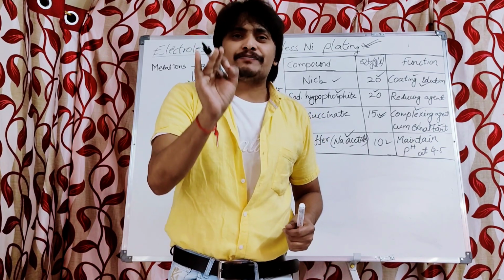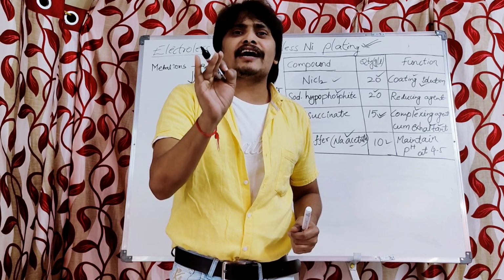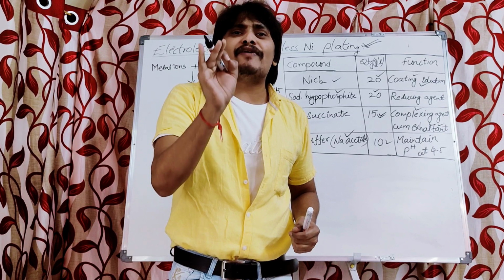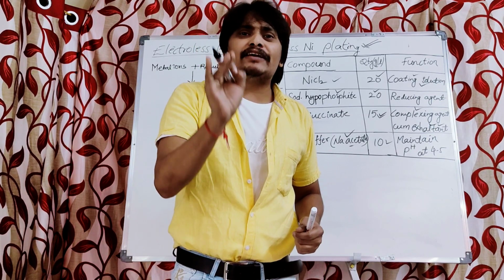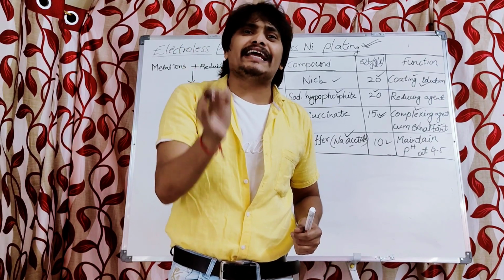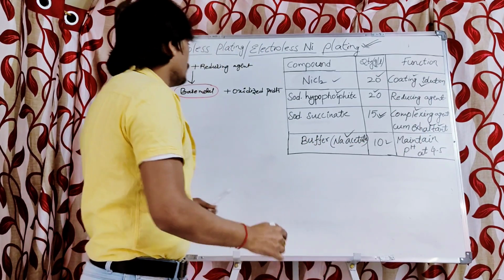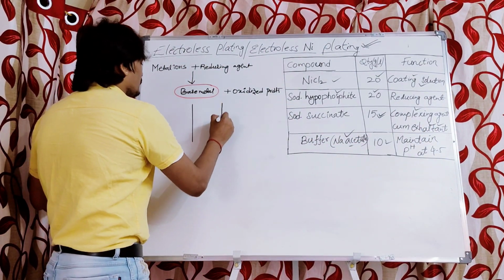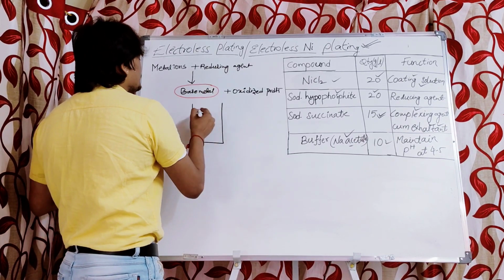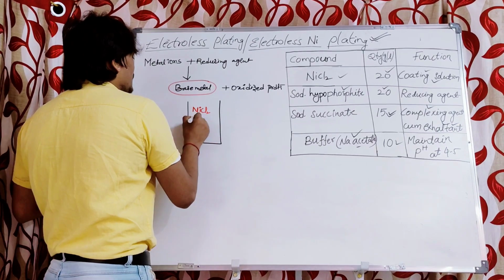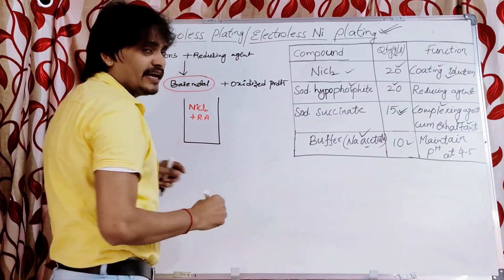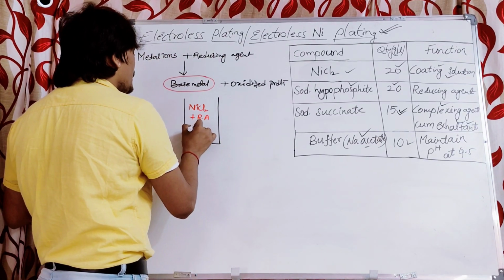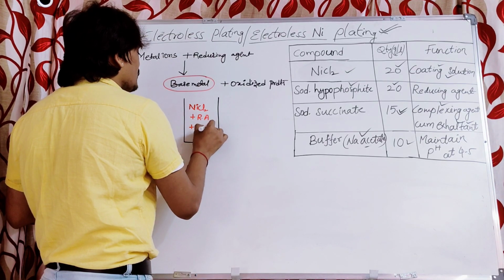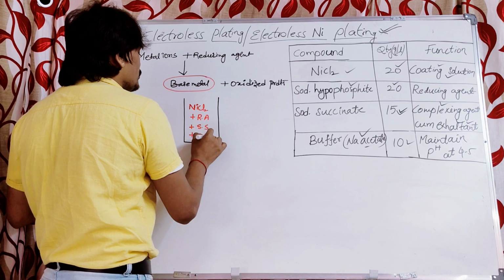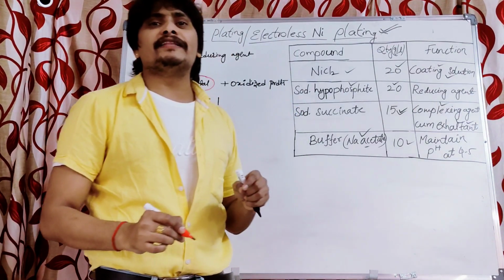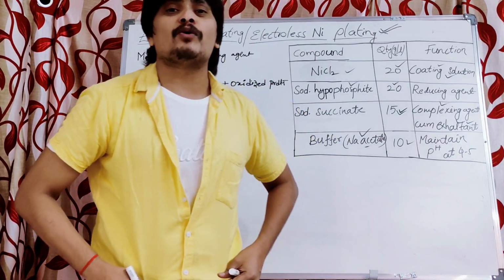Now the base metal will become free of all the impurities. The base metal which is now free of all the impurities is considered as the pre-activated base metal. Now this pre-activated base metal should be dipped or immersed into this composition bath. The composition bath comprises the coating solution, nickel chloride, plus the reducing agent. What is that reducing agent, students? The reducing agent is sodium hypophosphite. Along with that, sodium succinate should be used. What is the purpose? Already discussed. And sodium acetate is also used as the buffer solution in order to maintain the pH 4.5 in order to facilitate the reaction between the coating solution and the reducing agent.